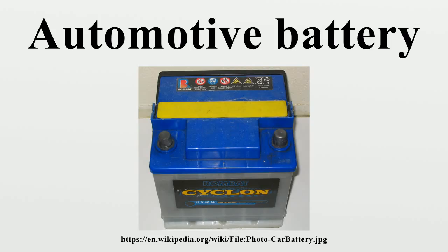Corrosion at the battery terminals can prevent a car from starting due to electrical resistance. The white powder sometimes found around the battery terminals is usually lead sulfate, which is toxic by inhalation, ingestion and skin contact. The corrosion is caused by an imperfect seal between the plastic battery case and lead battery post, allowing sulfuric acid to react with the lead battery posts. The corrosion process is also expedited by overcharging. Corrosion can also be caused by factors such as salt water, dirt, heat, humidity, cracks in the battery casing or loose battery terminals. Inspection, cleaning and protection with a light coating of dielectric grease are measures used to prevent corrosion of battery terminals.